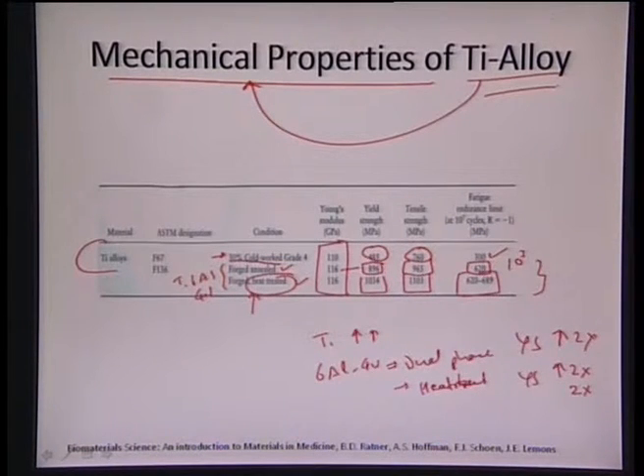So those are the advantages of utilizing titanium alloy and performing the heat treatment, because we can achieve very superior yield strength, tensile strength, and fatigue strength. Though the Young's modulus remains approximately the same and does not change much, the enhancement in the yield strength, tensile strength, and fatigue strength is just phenomenal.